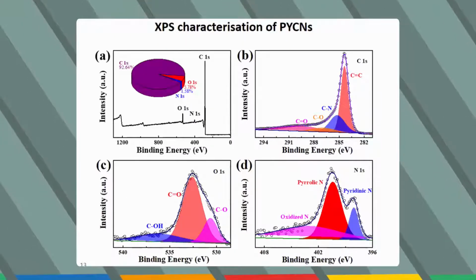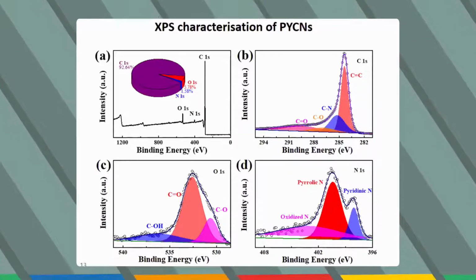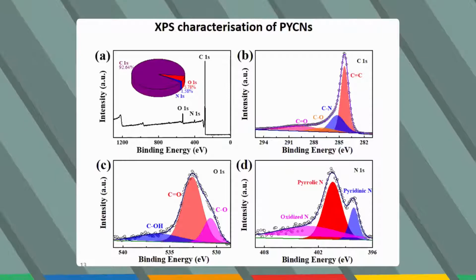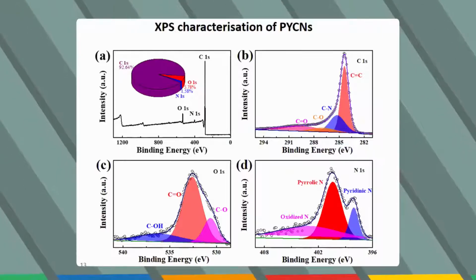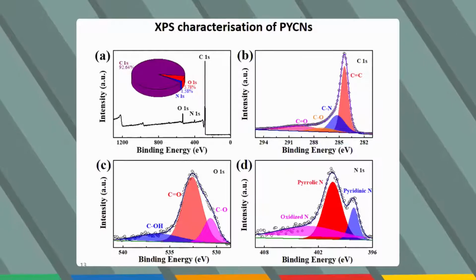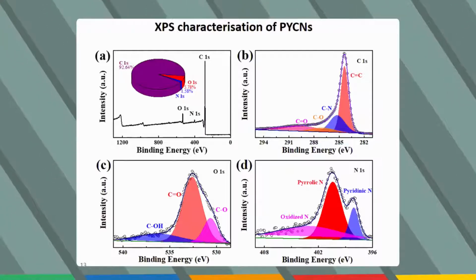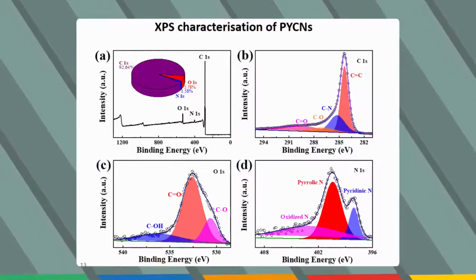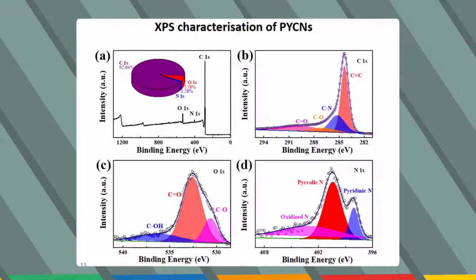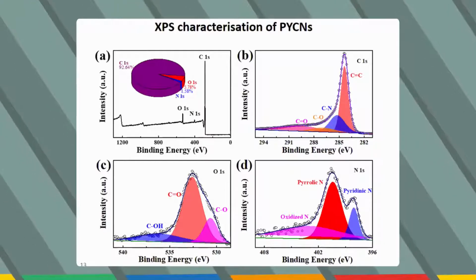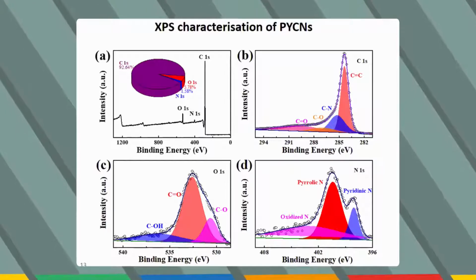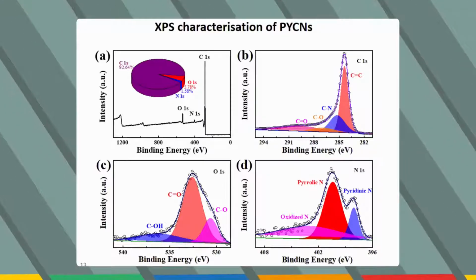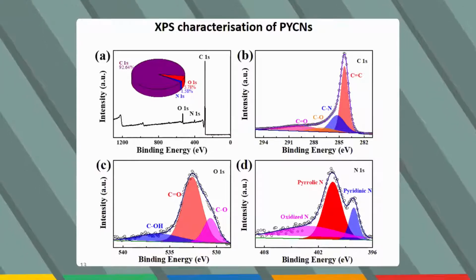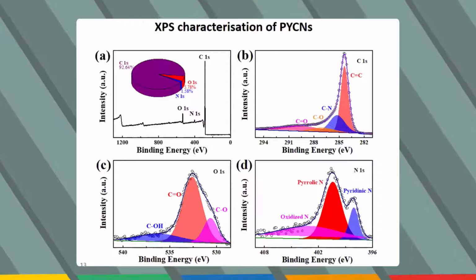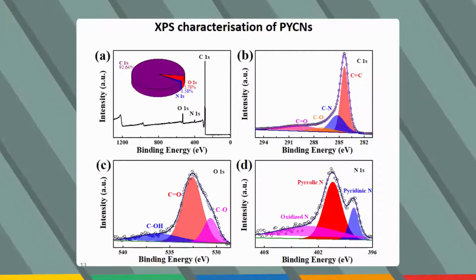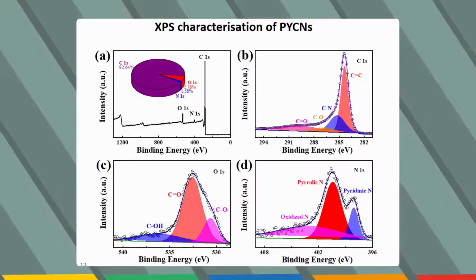We also did XPS characterization on these materials, and from the full scan we saw that over 90% was carbon, and nitrogen and oxygen were present in very minute quantities. But if we deconvolute the peaks for the carbon 1s, the oxygen 1s, as well as the nitrogen 1s, we can see that we don't have one type of material. We have a distribution of different types of bonds within the material itself.